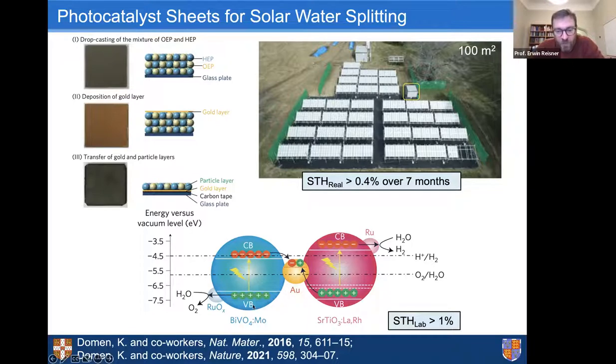And what Professor Domen has been using is molybdenum-doped bismuth vanadate as a light absorber and lanthanum-rhodium-doped strontium titanate as a second light absorber. And they're all joined by a gold layer that really allows regeneration and charge flux between these two light absorbers. So if you photoexcite the bismuth vanadate, you oxidize water with a ruthenium oxide catalyst to oxygen. The photoexcited electron regenerates the photoexcited strontium titanate, and the conduction band electrons here are moved to the ruthenium to reduce water to hydrogen.